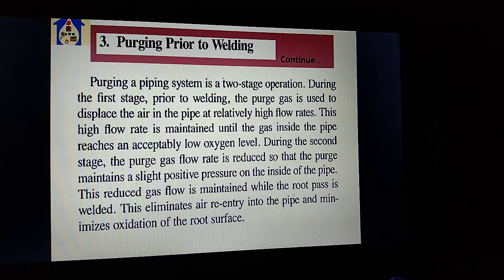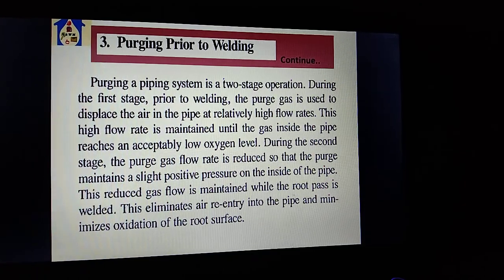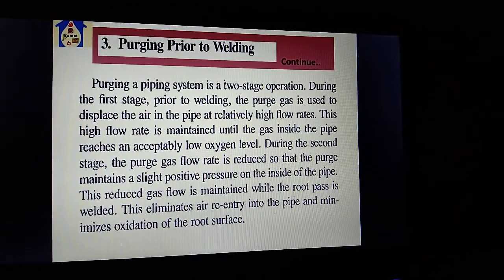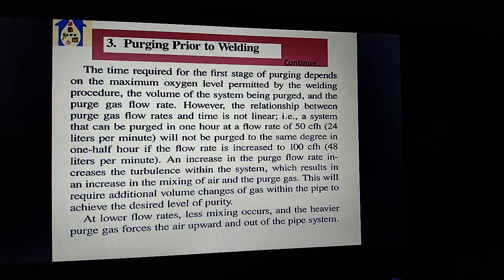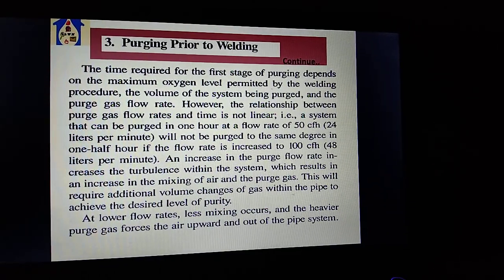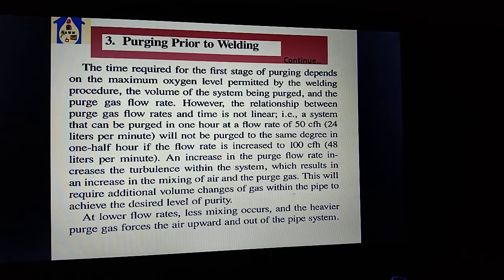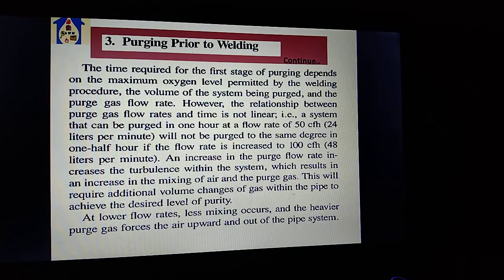The reduced gas flow is maintained while the root pass is welded, to eliminate air re-entry into the pipe and minimize the oxidation of the root surface. The time required for the first stage of purging depends on the maximum oxygen level permitted by the welding procedure, the volume of the system being purged, and the purge gas flow rate.